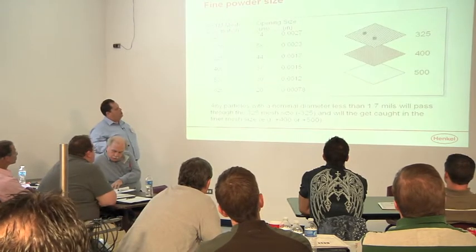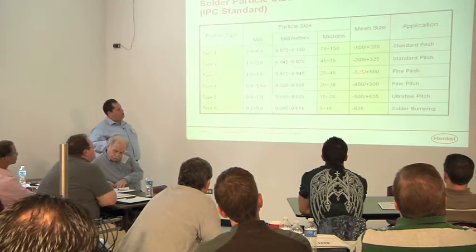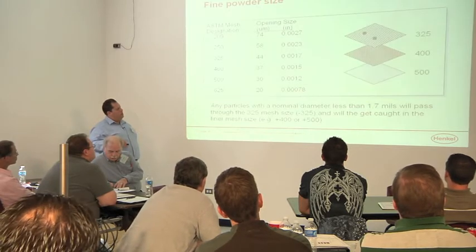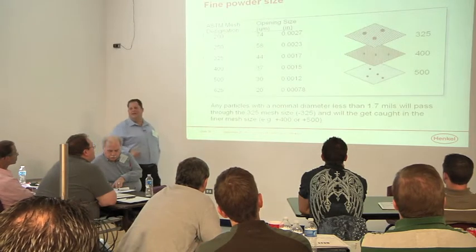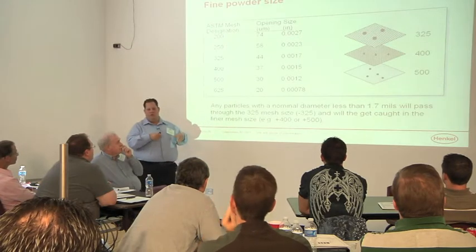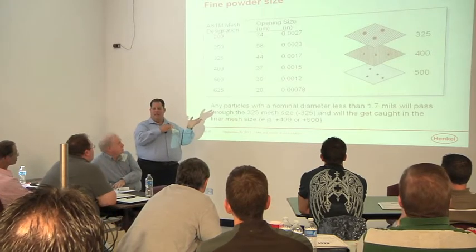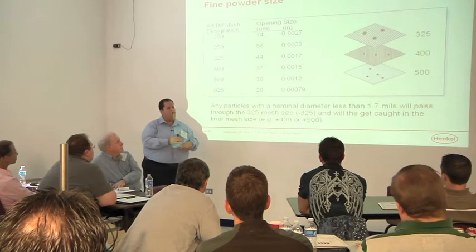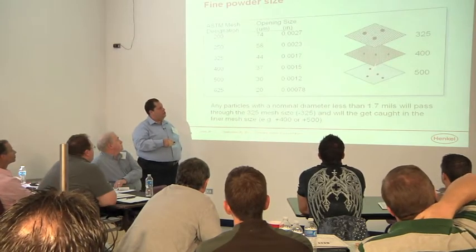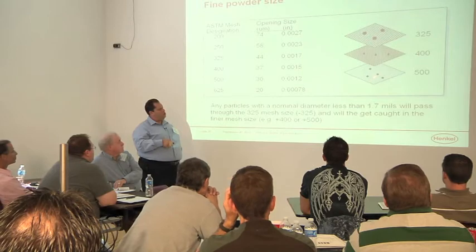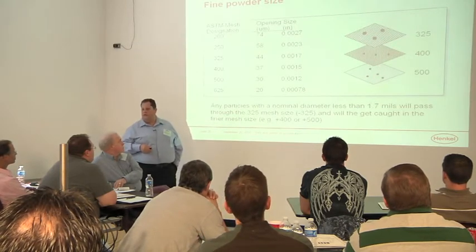You can see here - a little bit smaller particle size. Looking at these meshes, this is the old ASTM mesh designation. The larger particles get captured up top - that's why you see the minus 325. The smaller particles fall through the 400 mesh onto the 500 mesh. You're sieving them, trying to move them around, shuffling them. We've got these nice spherical components and we want them to stay nice and smooth and shiny, but that activity typically damages them. So we don't use this sieving method very much anymore. Traditionally, you drop that powder through a column with sieves - bigger chunks stay up top, smaller fines go through, and the rest in the middle you collect and make your paste from.